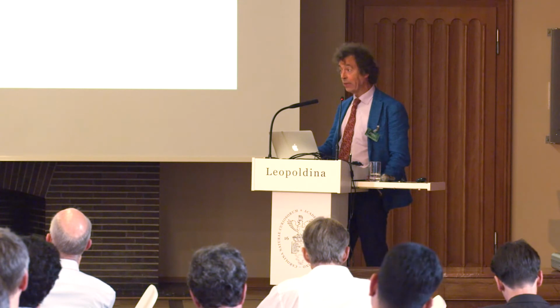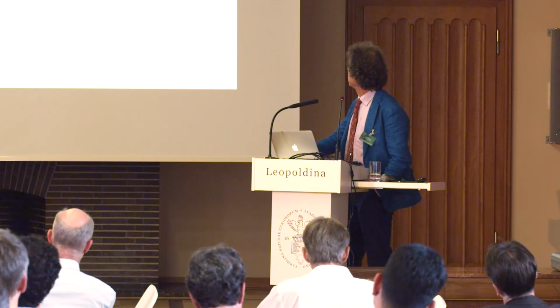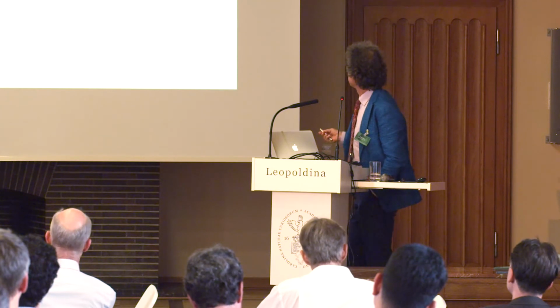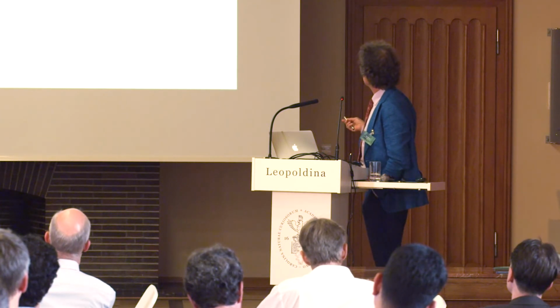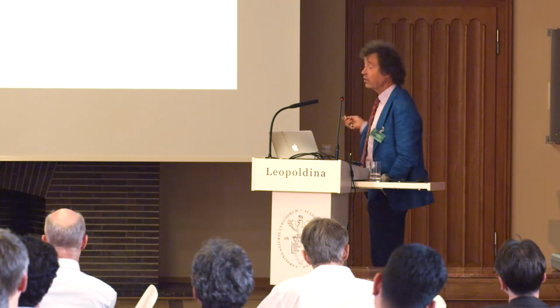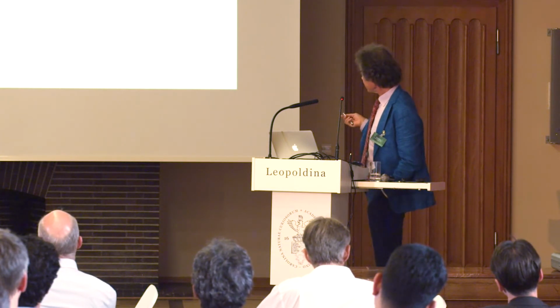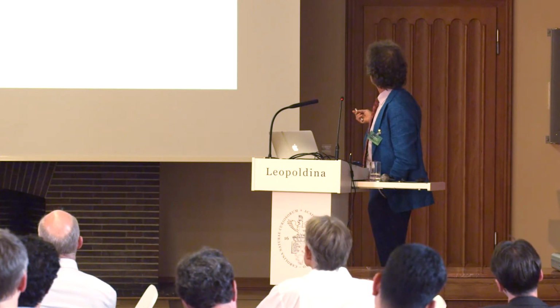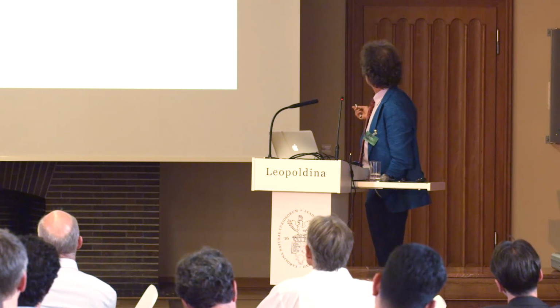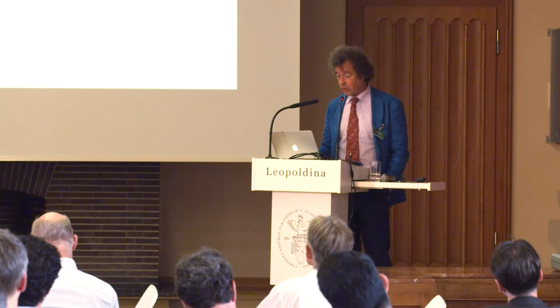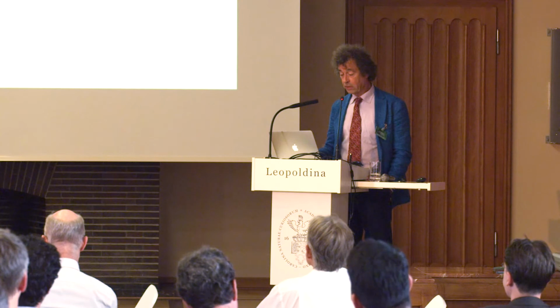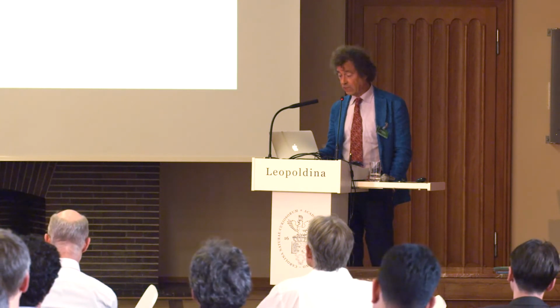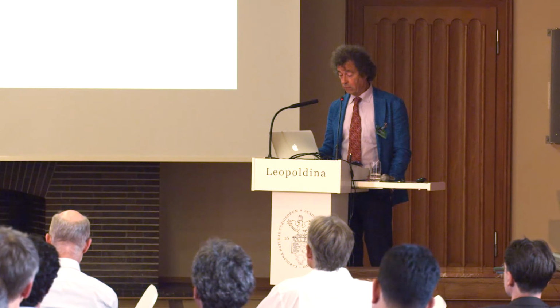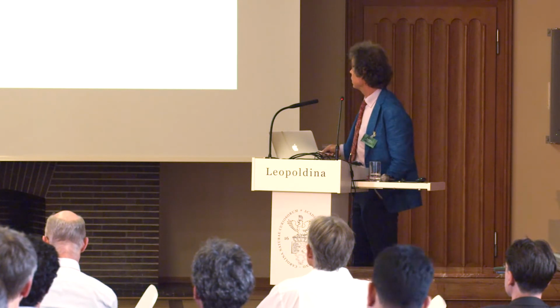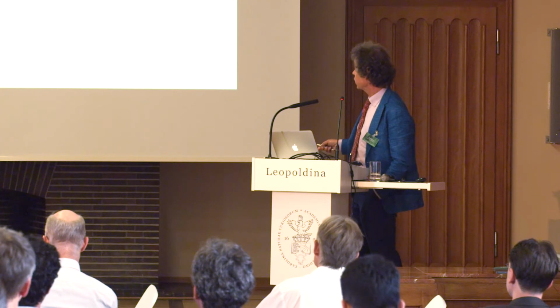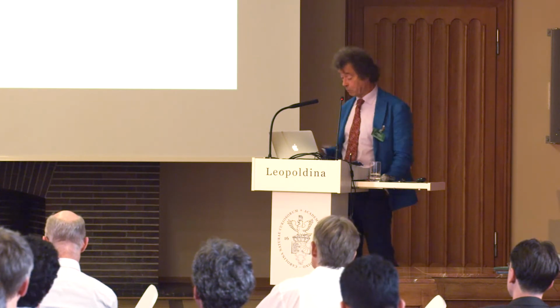And that is manipulating spins. How do we do this normally? Normally, you do that with a magnetic field. So we have an effective magnetic field that is given by an applied field, but also by interactions with the lattice, the spin-lattice relaxation, and also with the other spins. Usually you apply a magnetic field, and then you can change the orientation. Because it's a precessional motion, so it's a torque, the best way is to always apply a field perpendicular.